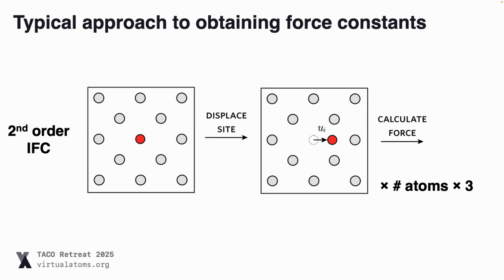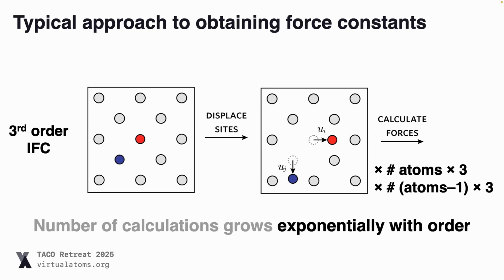Now, if we want to go on to third order force constants, and we heard a really good explanation of why we would want to do that yesterday, when we're interested in anharmonicity, so things like if we need to know the phonon lifetime, then the naive approach to doing this is you replace two sites. Unfortunately, as soon as you've replaced more than one site, you've broken the symmetry in the structure, so all of the other sites become inequivalent, more or less, and suddenly the number of deformations that you have to calculate grows exponentially. So even for relatively simple materials, this can quickly become thousands or hundreds of thousands of deformation calculations depending on the supercell size.